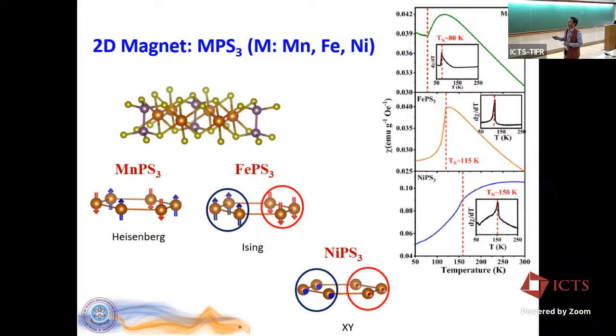Now, if we look at the magnetic state, all the 3 systems are antiferromagnetic below a certain temperature. So here are the magnetization, the susceptibility data measured on bulk crystals of these 3 systems, okay? Here the top one is MnPS3. You can see this susceptibility trend, and right around 80K there is this magnetic ordering. Below 80K it goes to an antiferromagnetic state. For FePS3 it is somewhere around 115K, below which it becomes antiferromagnetic, and for NiPS3 it's roughly about 150 Kelvin. These are the 3 different temperatures below which these 3 systems become antiferromagnetic.